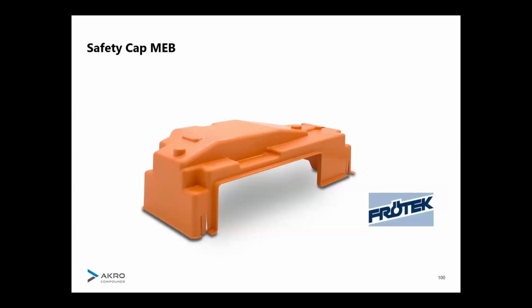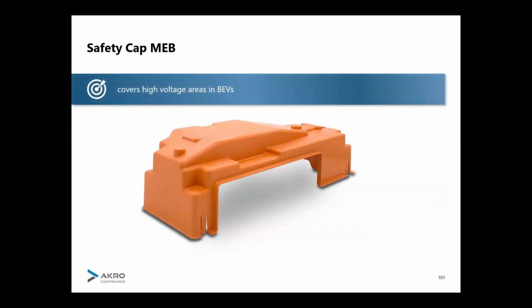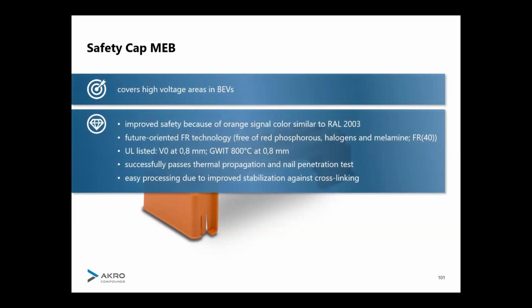Now we learned from the presentation before how important flame retardant requirements are. This piece is a safety cap in the MEB, from VW Group, the Modulare Elektrobaukasten. It's used in all these ID.3, ID.4 cars. And this was made in nylon 6. Now, because of the propagation test and the nail penetration test and all the tests you have, they decided to move away from the polyamide to polyketone. And of course, there's a reason why it's orange: this signal color, so that in case of an accident, the firefighters or whoever know where high current is, so this should remain a signal color and not become brown or something like this after a while.